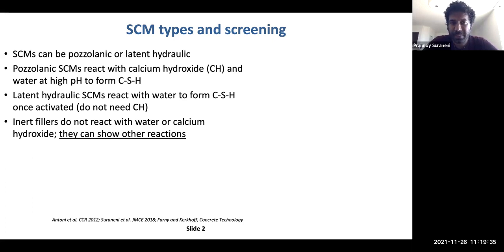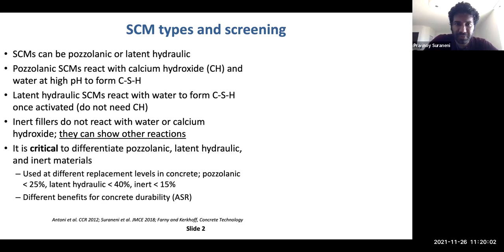Now, for pozzolanic SCMs, fly ash is an example. For latent hydraulic SCMs, slag is an example. These are differentiated from inert fillers. So inert fillers are materials which do not react with water or with calcium hydroxide. But this name can be a little misleading because they do actually show other reactions. For example, limestone is known to react with carboaluminate phases in concrete. But the big difference is that typically when using these materials, the replacement levels are extremely different. Latent hydraulic materials can be used up to 40% replacement. Pozzolanic, typically you limit to about 25%, and inert, you typically limit to about 15%.